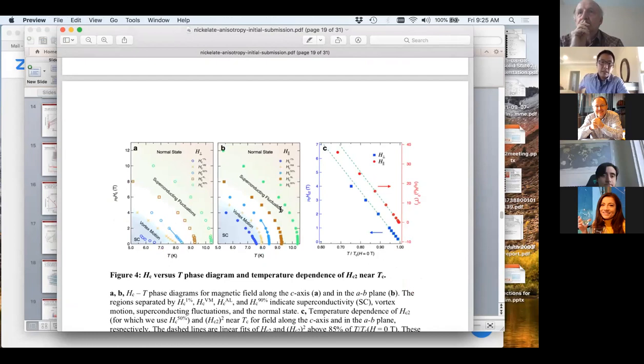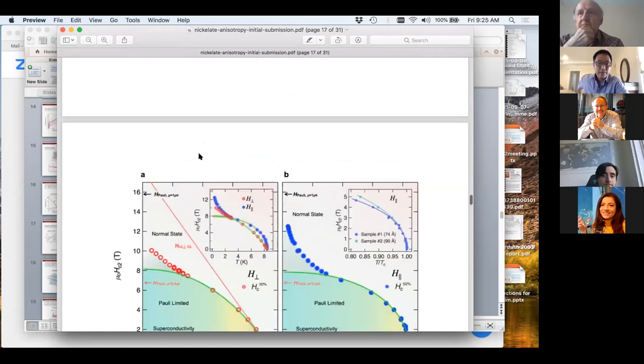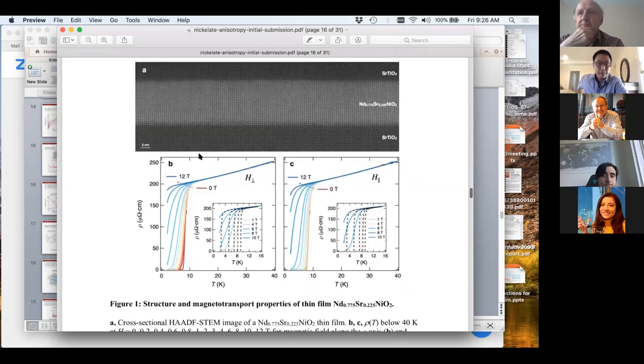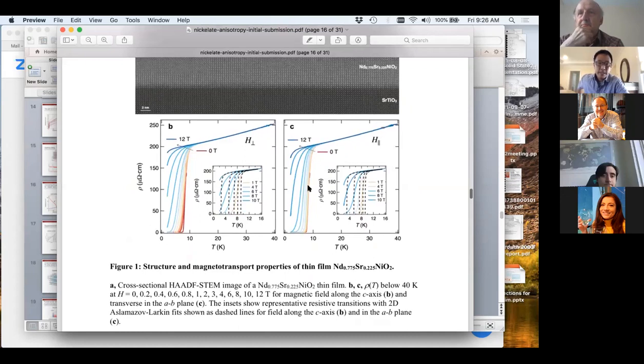Yeah, very good. Okay, I'm talking to an expert. So let me just say roughly, I can try to dig out more details, but let me just show you, for example, sorry, this is a bit busy. So this is the kind of thing that we were worrying about. One is that in the vicinity of TC, obviously we can worry about the onset of TC, we can worry about superconducting fluctuations. So these dotted lines are 2D Aslamazov-Larkin fits. Now I should say that I think our transitions are relatively broad. And so we can worry about intrinsic quantum fluctuations as well as just disorder broadening. So that's one issue about a very high transition temperature definition.